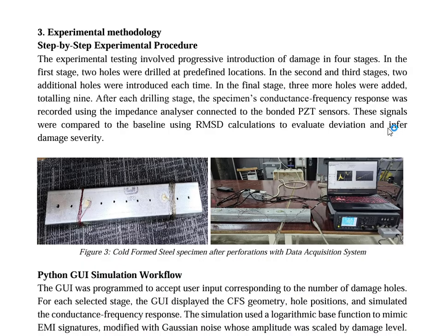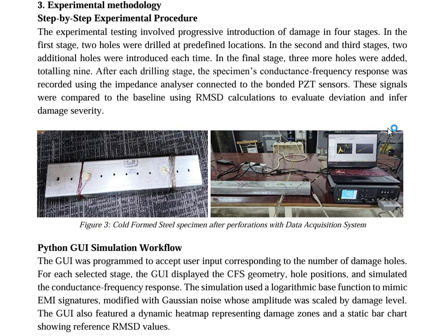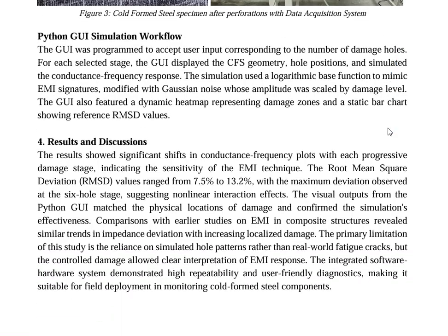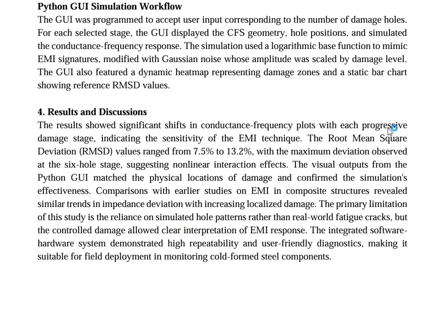Results and discussion. Our experimental data showed clear trends. RMSD values increased with more damage. The highest RMSD, that is 13.2%, was observed at the 6 hole stage, indicating severe damage. Interestingly, the GUI results followed the same trend, which validated our simulation model.